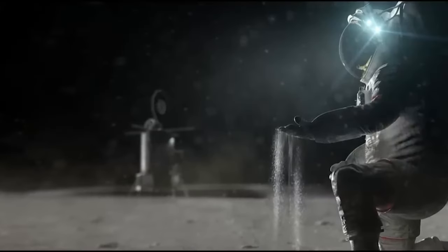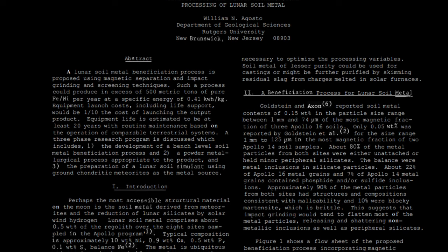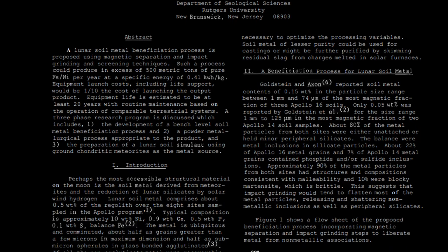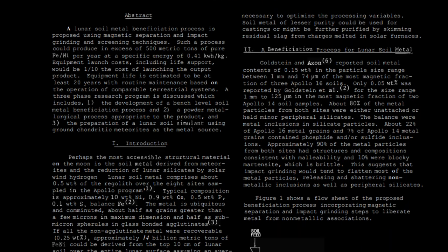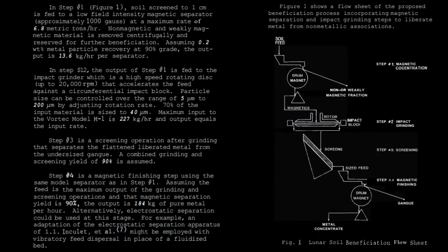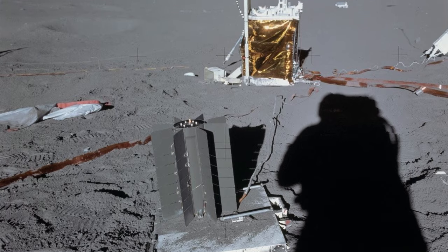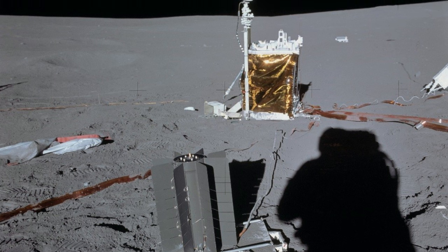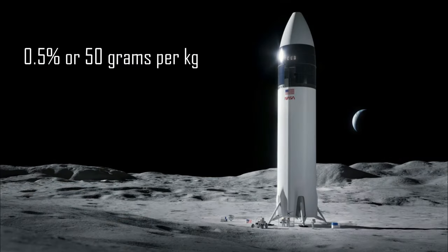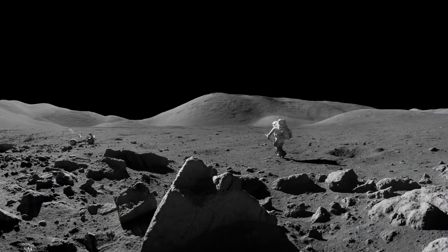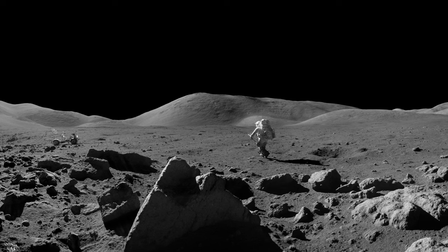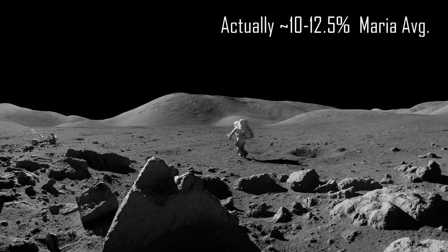Obtaining nearly pure iron from regolith is actually quite easy. You can just beneficiate free iron using the methods proposed in this paper from 1981, which uses impact milling and centrifugal magnetic separation to recover 90% pure iron. This method is easy, so it is likely the best early strategy. However, it's only able to recover free iron, which makes up just 0.5% of the regolith mass, so it does nothing for the remaining 99.5% of regolith, of which 11.5% is mineralized iron.